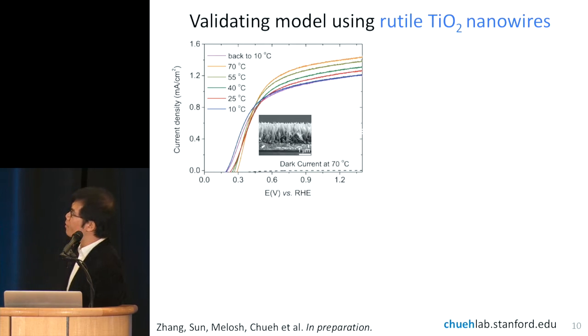So the next experiment, we thought, well, we should understand what's going on, and can we validate the model I proposed in the competition of light absorption between the space charge region and the minority carrier diffusion region. What we did now was to look at a third material, titanium oxide. And this is a very well established model system for studying photoelectrochemistry. The performance is typically not very good because of the large band gap, but nevertheless, we're able to see what is going on.